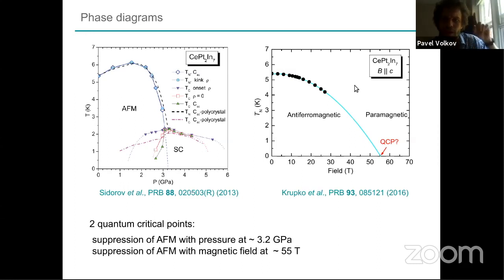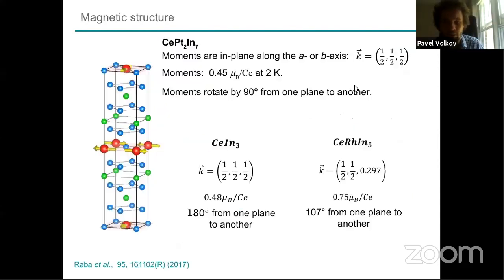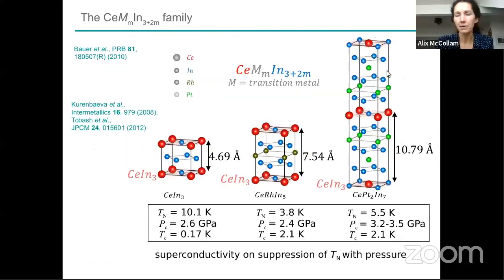But is there really anisotropy in the applied field, or did you measure only along C? Because it could be that some crystal field or something makes it very resilient against fields along C. Have you tried measuring other directions? So the system is quite two-dimensional, and so the anisotropy is larger than for the other materials.